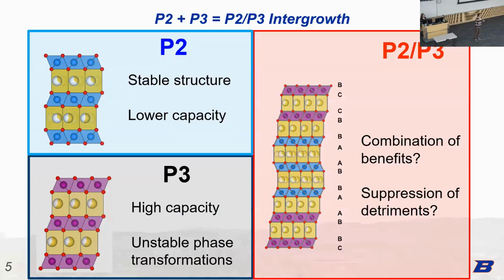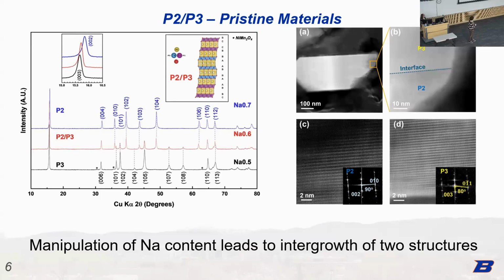So by theoretically combining the two of these structures, am I able to get a combination of these benefits while suppressing the detriments? How I actually instigated this intergrowth material, where you have two phases within the same particle, is I simply varied the sodium content in my battery. And what I found was that when I increase the sodium content, I go from a pure P3 structure, this is with X-ray diffraction, to an intergrowth P2, P3, and then a pure P2. And with transmission electron microscopy, I can actually visualize that these phases are growing within the same particle. So it's not just a simple mixture of P3 particles and P2 particles. You're actually having them grow simultaneously as the material is synthesized.